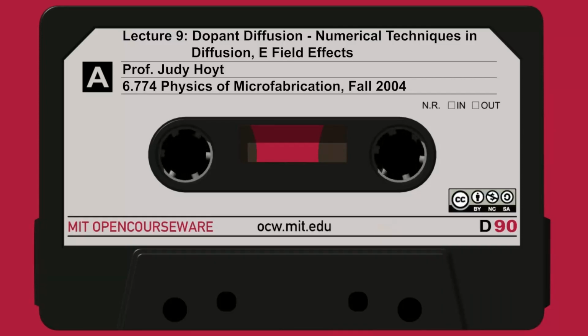And you see that in the middle of the slide, and then we substitute in that the dopant concentration Nd is equal to C. And we're able to see then that the total flux is the usual Fickian term, minus D times partial C partial X, minus this other term, which ends up being able to be written in terms of partial C partial X times the H factor, where H is equal to, as shown on the bottom, 1 plus C over the square root of C squared plus 4Ni squared. So that just justifies the derivation of the H factor on slide 22.